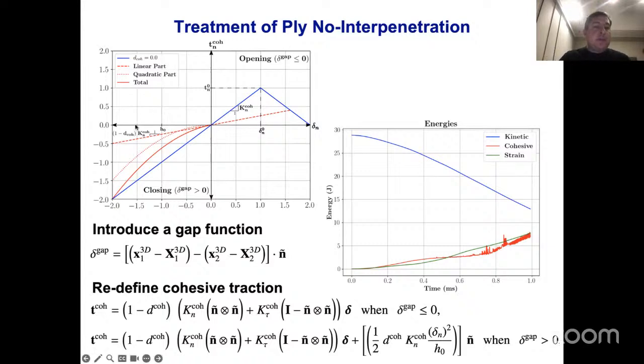And what happens in this case is, as you switch from opening to closing, the local stiffness changes. And so when it comes to implicit procedures, these become very hard to converge, because in the case when you have a highly dynamic event and the plies are chattering, you go from opening to closing. Your stiffness changes locally and it drives your Newton solvers crazy. And so what we did, we changed the constitutive behavior in the normal direction.